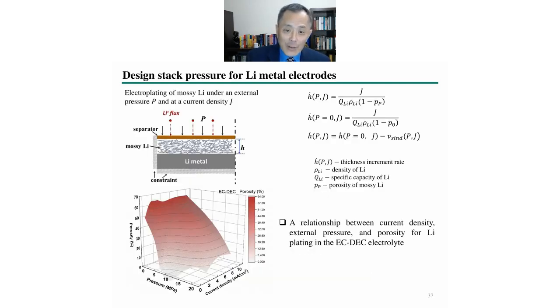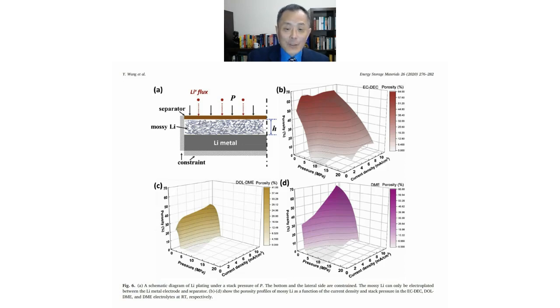These measurements allow us to build a model for the conditions at which dense lithium may be formed, by considering the deposition rate, which is related to the current density, and the creep rate, which is related to the porous structure of lithium. The result is that the porosity is a strong function of the applied pressure, and it's also a function of the electrolyte used. Under the same pressure, different electrolyte additives can also influence the porosity of this lithium metal.